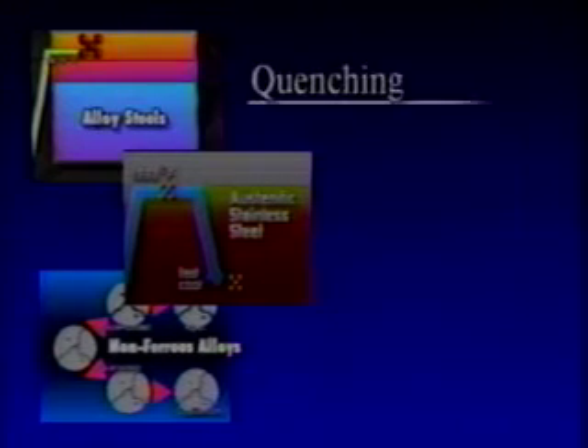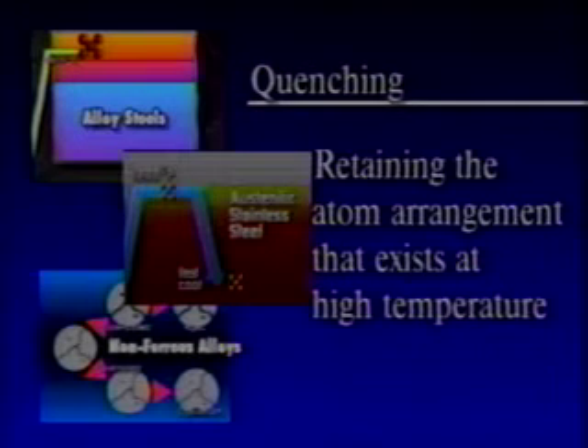So we see that in all classes of alloys, the carbon and alloy steels, the austenitic stainless steels, and the non-ferrous alloys, the quenching process is actually a means of retaining the atoms in the arrangement that exists at the high temperature. In effect, what quenching does is freeze the high temperature structure so that it can exist at room temperature.